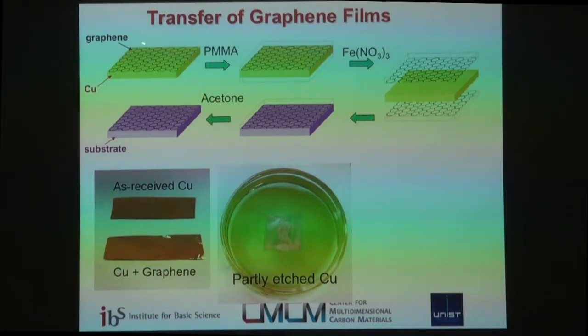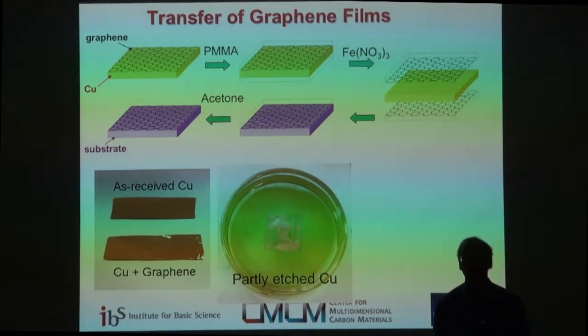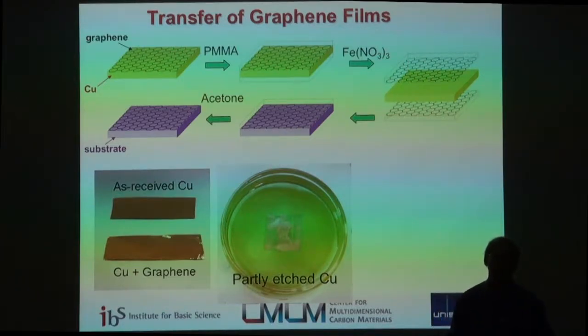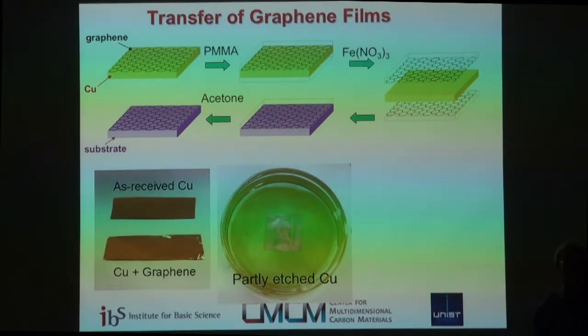So we grow mostly monolayer graphene in our initial efforts on copper foil, so it's polycrystalline, it's not a single crystal. Recently there was an important finding in Jiwoong Park's group at Cornell that if you buy a particular copper foil from a Japanese company, Nilaco, and you heat treat that, you can convert the whole foil, which is about that long and about that wide, to copper 111. So I think this is an incredibly important breakthrough. If you have questions about that, I'd be happy to discuss that too.